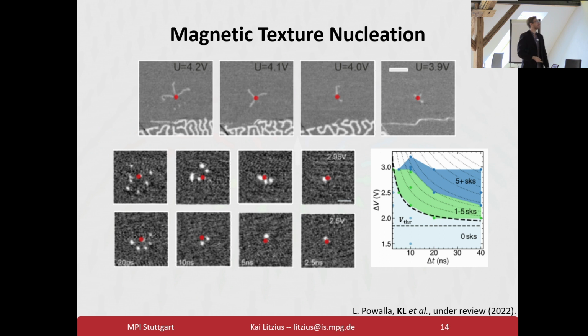Okay, but not so interesting. But if we apply AC current pulses in the nanosecond regime, we don't generate stripes anymore, we just generate skyrmions, and exclusively skyrmions. The number of skyrmions depends on the voltage of the pulse and the duration of the pulse, and can be tuned from a single skyrmion up to a sparse array around the contact, which always follows a certain outline. There seems to always be a circular area, a ring, where the skyrmions are formed, and everything else, inside the ring or outside the ring, is not written.